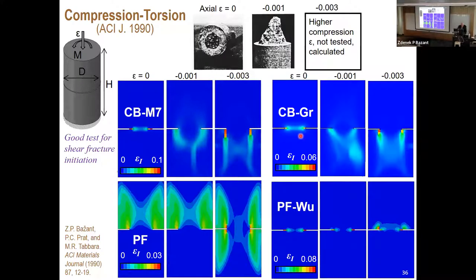Another test which has been overlooked, Northwestern, we tested 1990, compression torsion. So we take a specimen, put it under compression, and then apply a torque, and we do two cases, with compression and without. If there's no compression and there is a circumferential notch, the torsion results in a perfect mode three crack plane. Now, if you apply compression of about 40% of the strength, you get a cone.